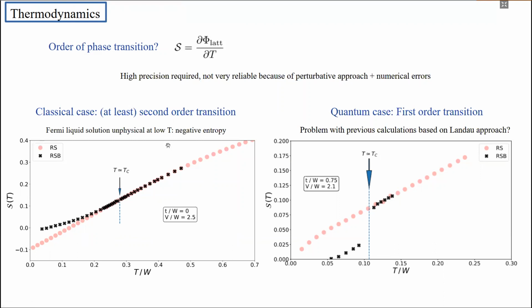Okay, so on the left-hand side, you see what we get in the classical case. So this is just basically the case when the hopping is 0. So we have a Sherrington-Kirkpatrick model at hand. With dots, you see a solution obtained within the assumption that the distribution of the Hartree fields remains Gaussian. As I already argued, this assumption is actually wrong at low temperatures and leads to an unphysical solution, which is very clear from here since we get a negative entropy at low temperatures. These crosses show the real physical solution, and that goes to 0 as T goes to 0, as it should.